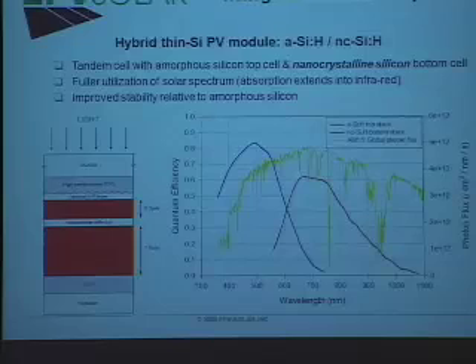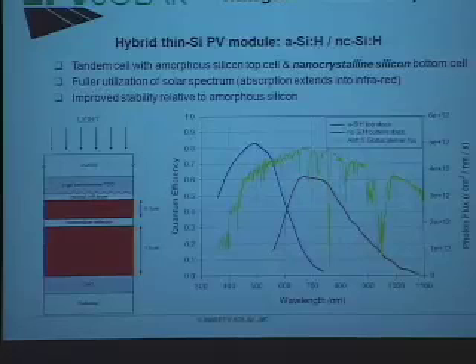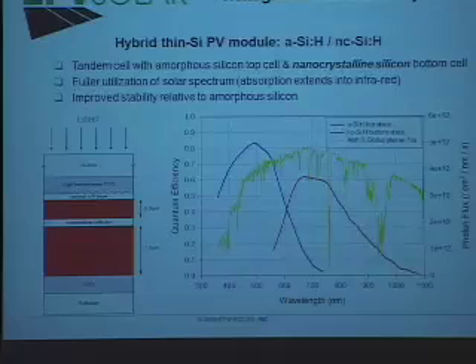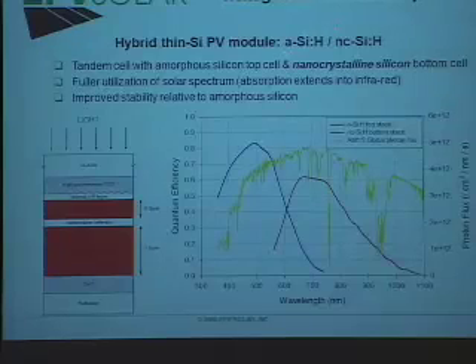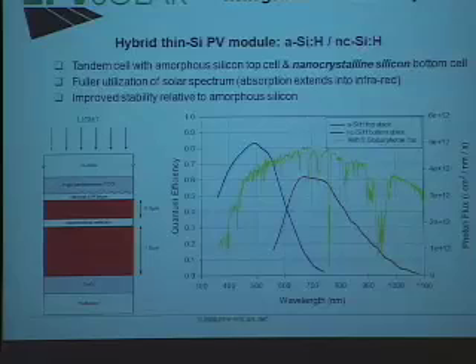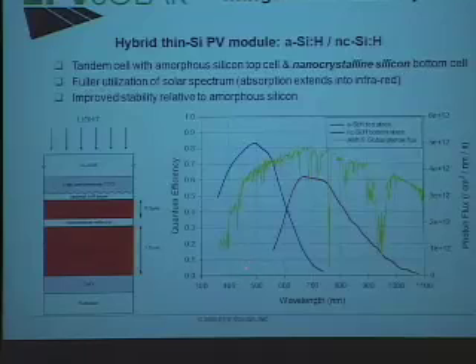Okay. Now, what is the next generation product? How is that going to be different? We're going to build on the amorphous silicon technology that I just described. Hydrogenated amorphous silicon. The hydrogen is in there to passivate defects. And we're now going to make a hybrid module with nanocrystalline silicon. And the motivation for putting in nanocrystalline silicon is that it has a lower band gap and hence is responsive in the infrared portion of the spectrum.